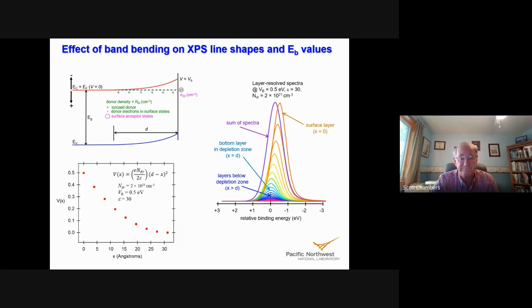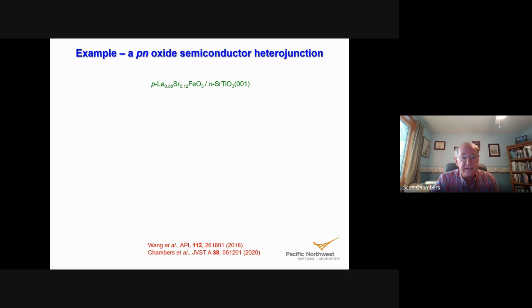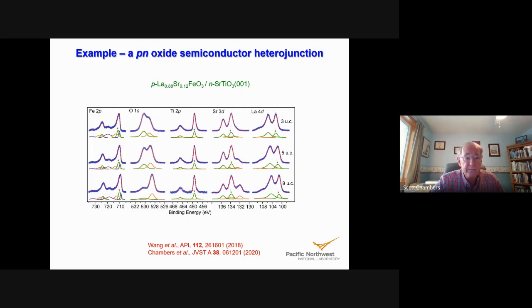Yeah, absolutely. All right, so we're going to start with lanthanum ferrite, and we're going to alloy 12% strontium onto the lanthanum site. That's a p-type semiconductor, it turns out, and we're growing it on an n-type semiconductor substrate, strontium titanate. Okay, here are the spectra. And notice, there's some interesting things.